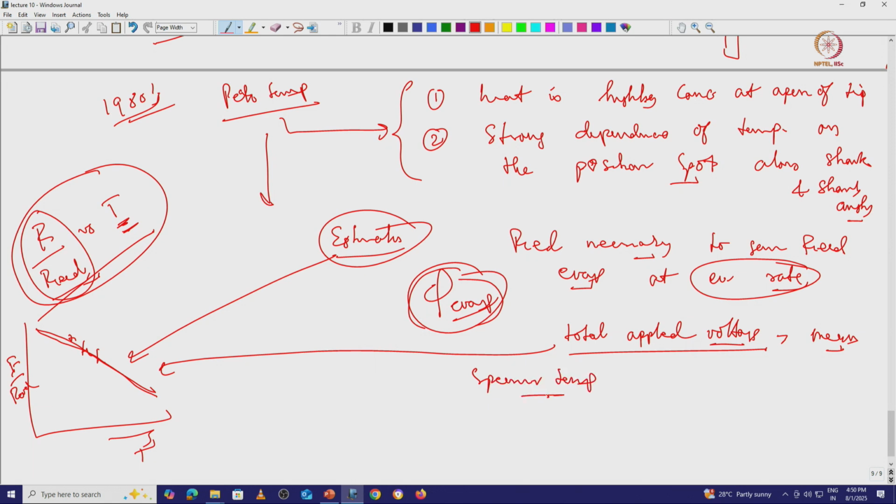With this technique, the peak temperature can go from 50 Kelvin to 500 Kelvin depending upon the illumination condition. This is one method used to estimate the peak temperature of the tip surface during laser pulsing.